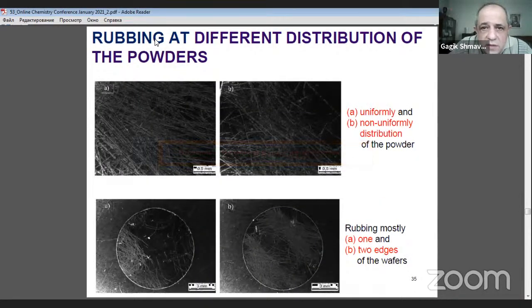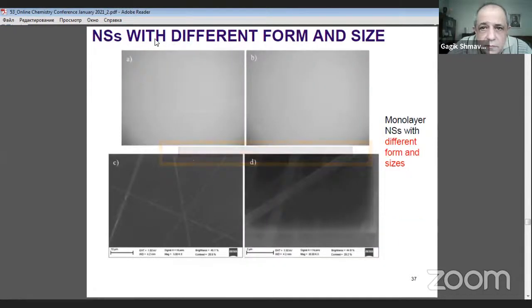Rubbings are carried out with different distributions of powders, so you can see uniformly distributed and non-uniformly distributed powder, and rubbing mostly on one or two edges is carried out as well. We use different applied pressures on the substrates, and you can see that the rubbing also depends on the applied pressure.